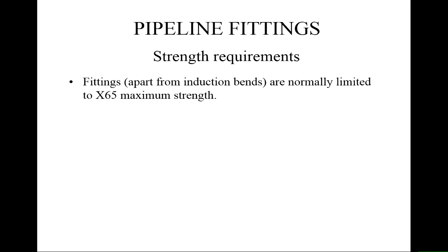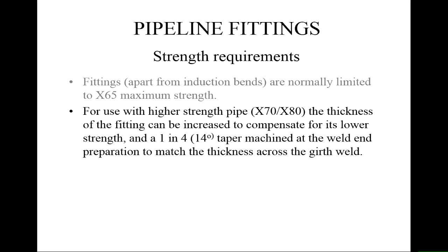So fittings, as far as I'm aware, are normally limited to X65 grade maximum. For higher strength applications, you have to increase the strength of the fitting, and you can't do that, so you have to increase the thickness of the wall. Generally that means you have a mismatch between the thickness of the line pipe and the thickness of the fitting, so you have to have a gradual change in thickness by putting a taper onto the end of the fitting. So 1 in 4 taper, 14 degrees, and it's made at the weld preparation stage.